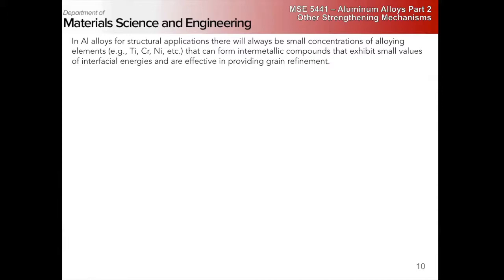I have a question about grain refinement. I've read that grain refinement is one of the ways to circumvent the strength-ductility paradox. I understand why the strength is increasing, but having a pinning particle at the grain boundary, how is that not detrimental? Well, remember grain boundaries, it's hard to pass dislocations through grain boundaries anyway, right?